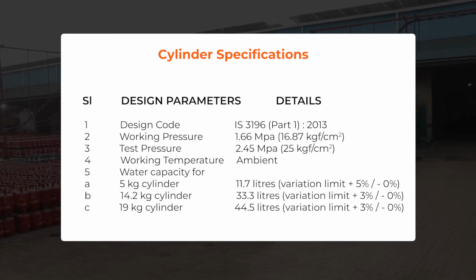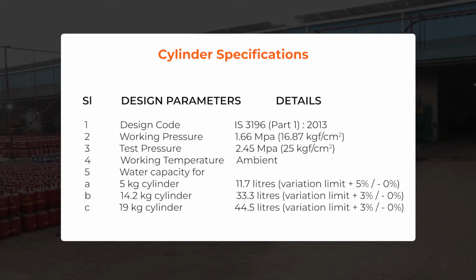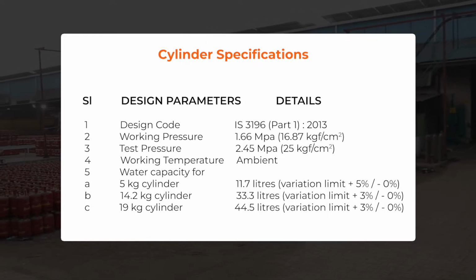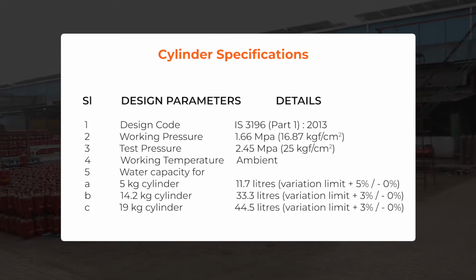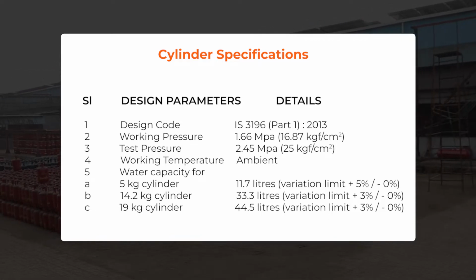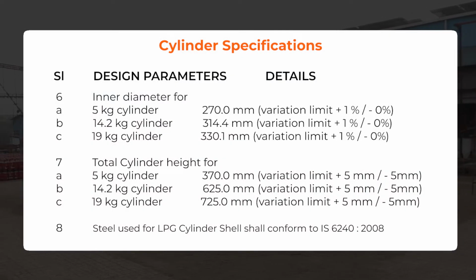14.2 kg cylinder 33.3 liters. Variation limit plus 3% minus 0%. 19 kg cylinder 44.5 liters. Variation limit plus 3% minus 0%. Inner diameter for a 5 kg cylinder 270.0 mm. Variation limit plus 1% minus 0%.